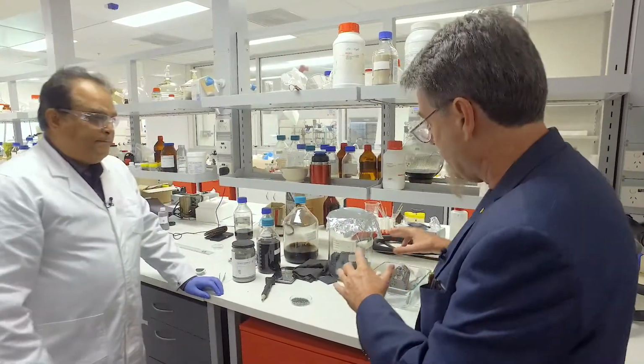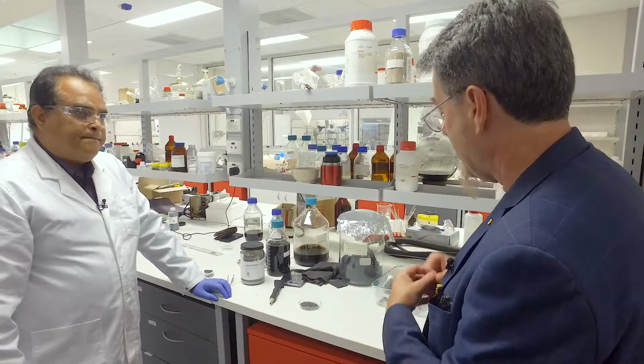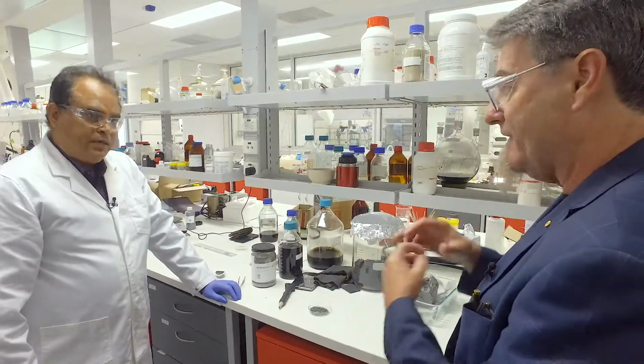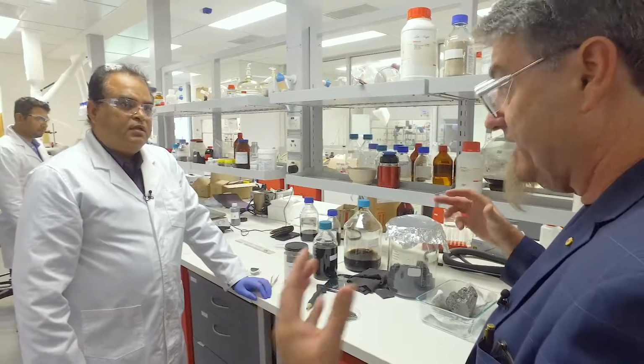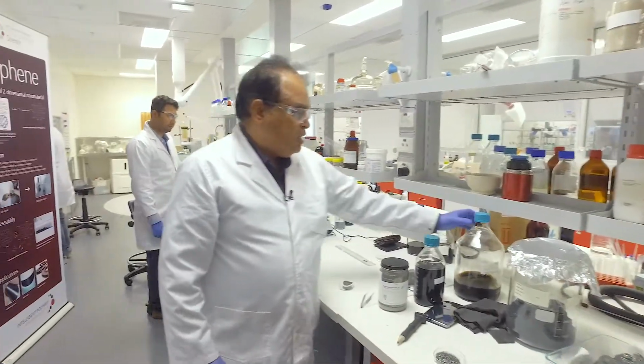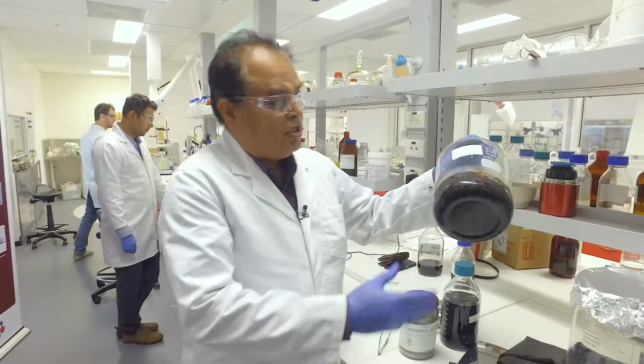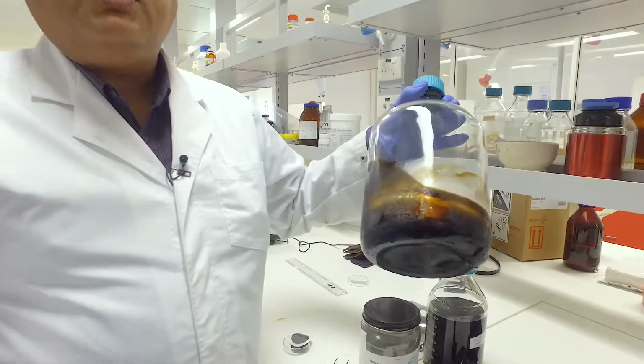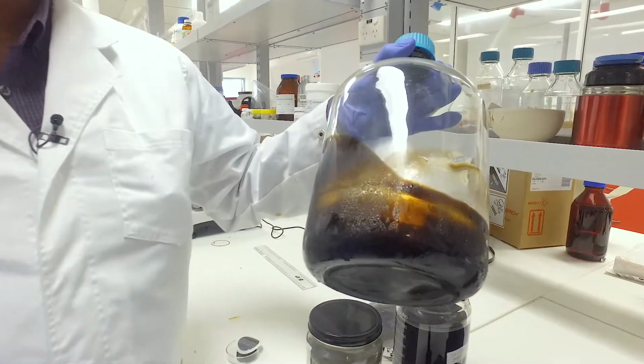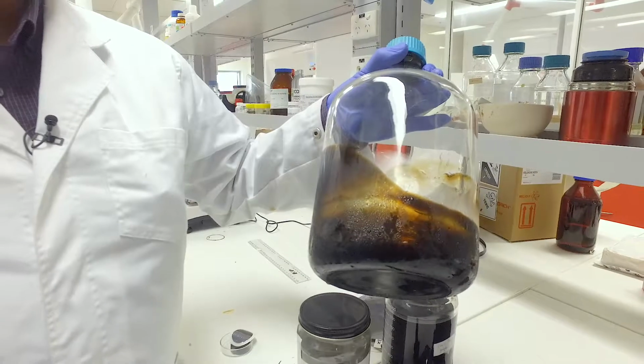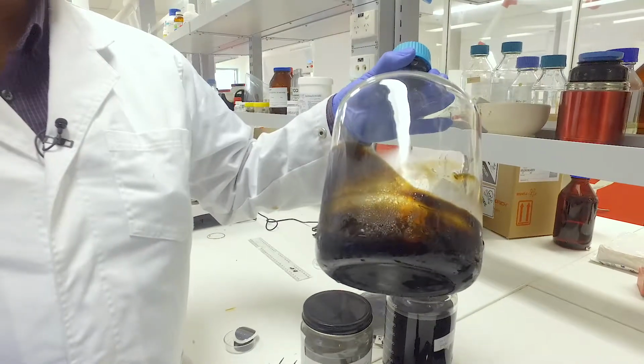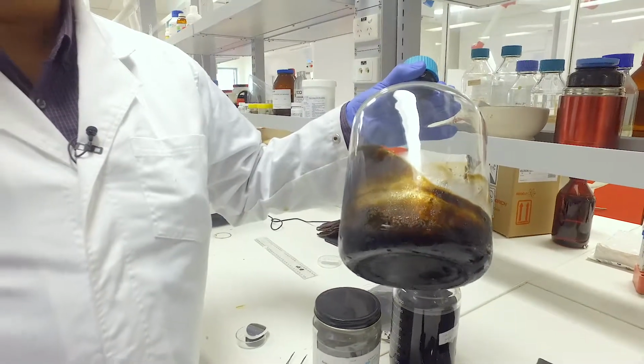Right, so now we've got this thermally expanded material and we're going to chemically oxidize it. And does that cause it to break up into the individual sheets of graphene? Absolutely. This is what we have been getting. This is the graphene oxide, which is a very large sheet of graphene oxide, around 50 to 70 micron sheet, which has a unique property, forming the liquid crystalline nature of the material as well.